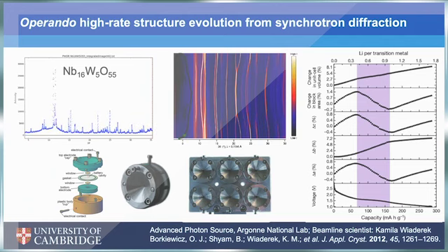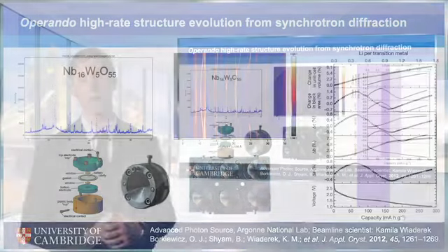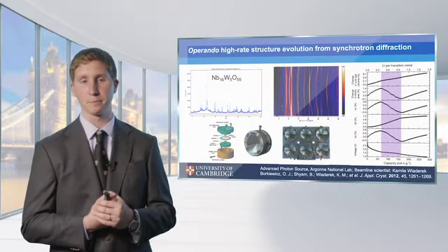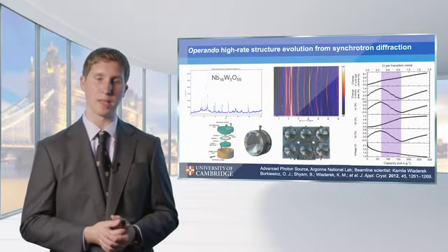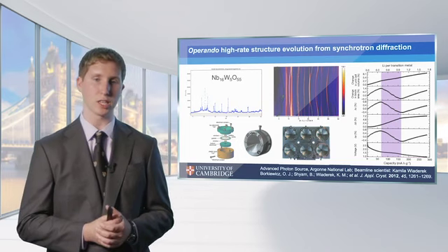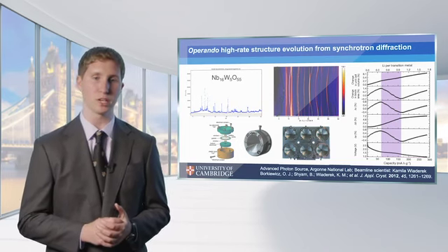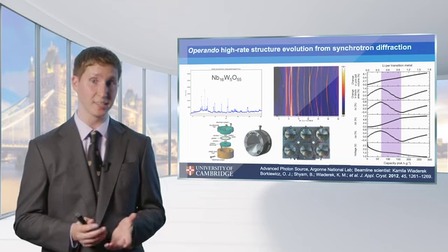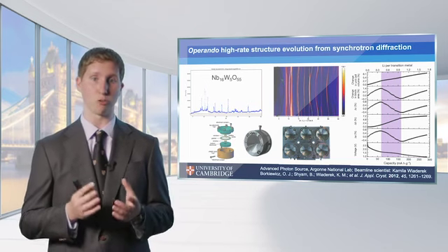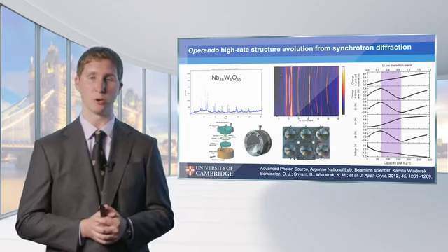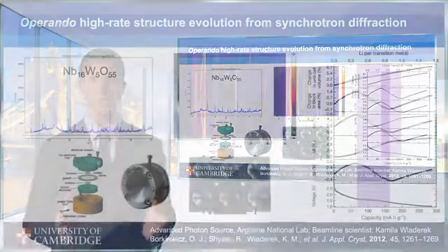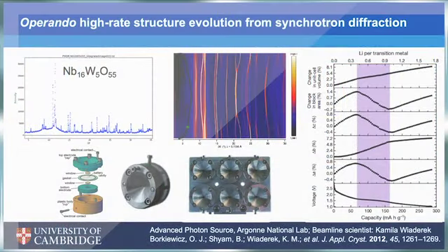So we want to be sure that what we're measuring in the X-ray beam is the same as what we would be measuring in the lab. And so we do that here. And the other advantage then of going to a synchrotron like the APS is that we're able to collect a diffraction pattern every couple of seconds. And so that means we can actually measure real-time high rate, charge-discharge cycling in, say, 6 minutes, and we can record hundreds of diffraction patterns in that time, and then be able to get this really precise look at how that atomic structure is evolving.